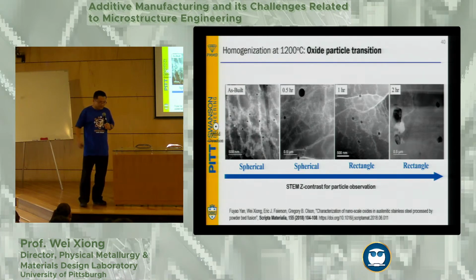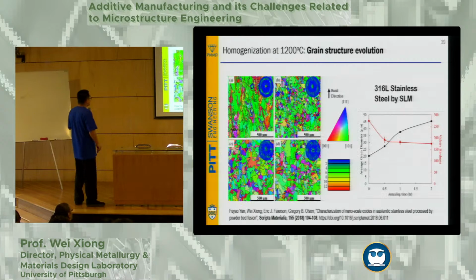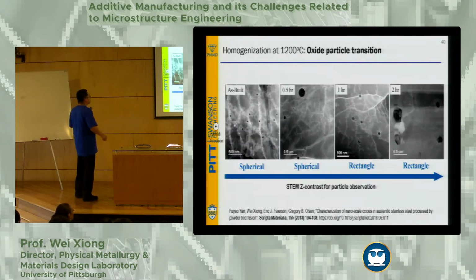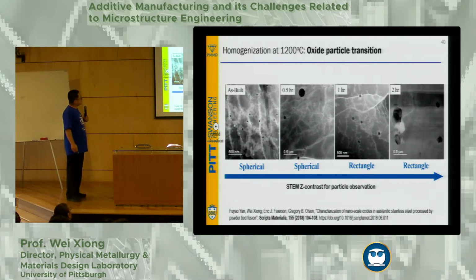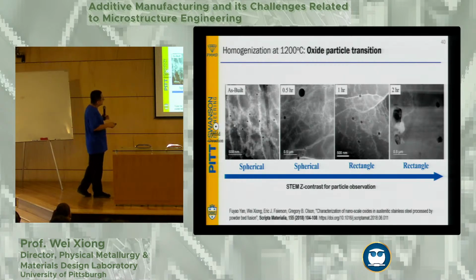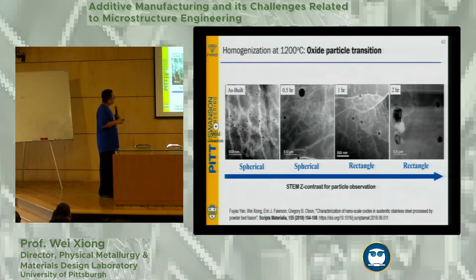We looked at the microstructure with EBSD, and we also checked with TEM. Once we went to the TEM study, we checked all of these possible precipitations. So this is the printed one, initial - we find a lot of small dots, and they're also spherical in shape, tangled with dislocations and the cellular boundaries.